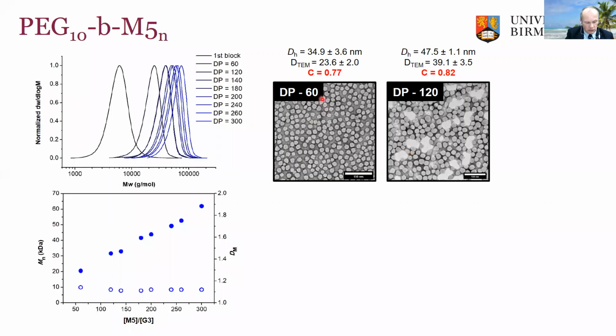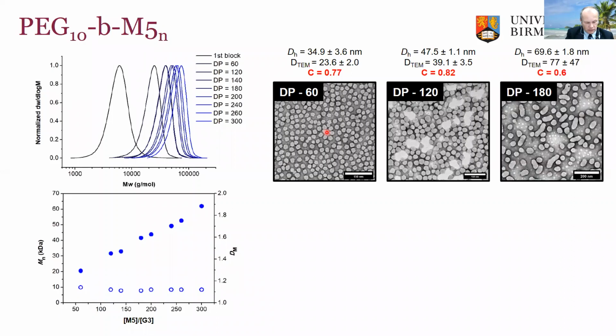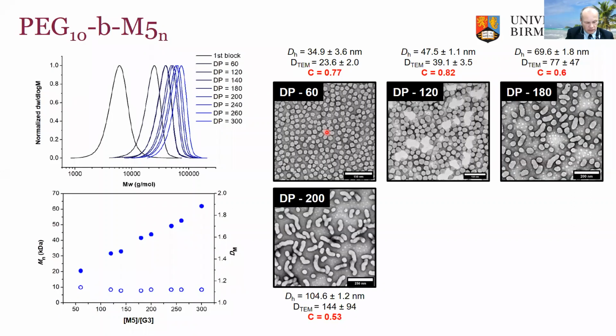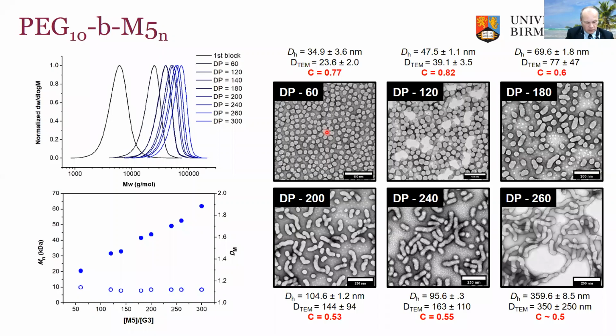Interestingly, for the PEG-based system, we observe something different. So if we start here at a DP of 60, and then at DP 120, we still have particles that increase in size. We still have a circularity index that suggests they're still relatively spherical. That starts to decrease quite dramatically, and hopefully you can see clearly from the TEM images that we start to form these worm-like structures, and we term these tubosomes. So these now are elongated, long structures that have formed from the original polymersomes for this PEG-based system.